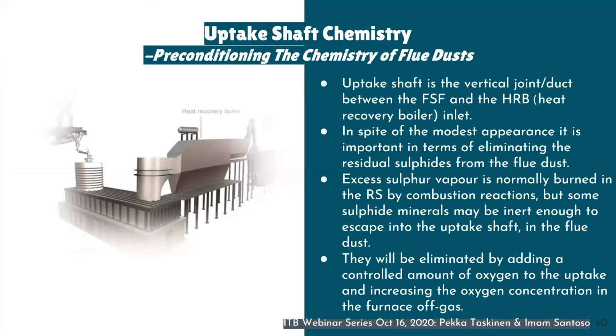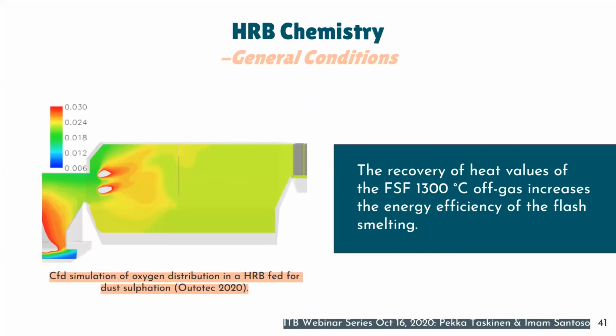And this uptake shaft, which is connecting the settler with the heat recovery boiler, is the first part of the flue dust management. There we oxidize all sulfidic particles which may be present in the flue dust, so adding a controlled amount of oxygen from here, sulfides are oxidized, and that is important for the next step of the flue dust management, which is taking place in the heat recovery boiler.